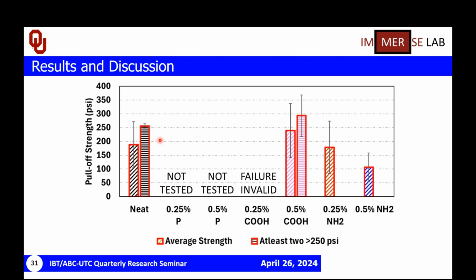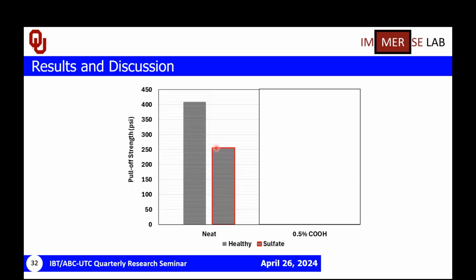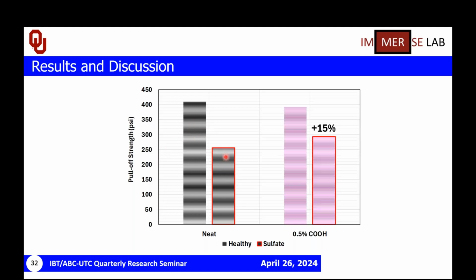In this figure, you can see the comparison of the pull-off strength of the neat polymer concrete, which had the healthy substrate and unhealthy substrate. As you can see, when we had the unhealthy substrate, the pull-off strength decreased. Also, in these 2 bars you can see the comparison between the healthy and unhealthy substrate, with the 0.5% COOH polymer concrete on top of that. As you can see, the unhealthy substrate showed lower pull-off strength. And in comparison, when we have the deteriorated or unhealthy substrate, using the 0.5% COOH carbon nanotube increased the pull-off strength by 15%. It shows that if we use this type of functionalized carbon nanotube, we can have a higher pull-off strength in an unhealthy situation.